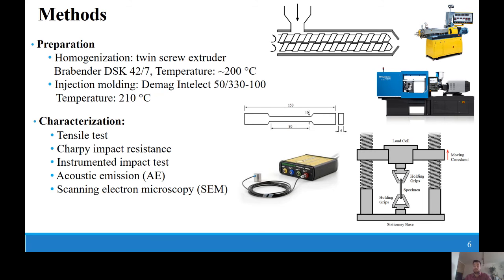The components, the fiber and the matrix polymer, were homogenized in a twin screw compounder. PVA fibers were dried before extrusion at 80 degrees Celsius for 4 hours in a vacuum oven. Extrusion was repeated once in order to increase the homogeneity. The granulated composites were injection molded into standard tensile bars. The specimens were stored at ambient temperature for 1 week before further testing. The mechanical properties of the composites were characterized by tensile and impact testing. The structure of the composites and deformation mechanism were studied by scanning electron microscopy, by recording micrographs on fracture surfaces created during tensile and fracture testing, respectively, and by acoustic emission measurements as well.